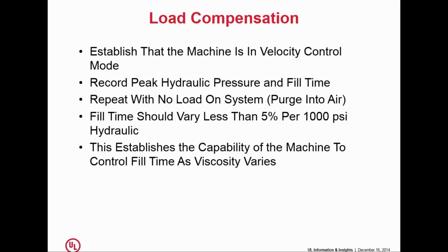We all know that. Two other things I want to mention about injection unit specifications before we move on to the sprue. And that is, first of all, you need to make sure that your system is load compensated. What I mean by that is, if you're running under velocity control and it's taking you 2 seconds to fill the mold, to fill it the way we consider filling in scientific molding, which is 95, 96, 98% full, if it's taking 2 seconds to deliver that material to the mold, then when you pull the injection unit back and on cycle, you shoot that same volume of material into the air with no resistance, it should take the same 2 seconds.